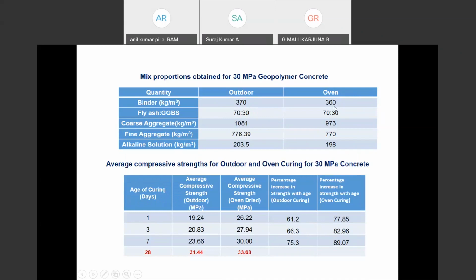If I go for oven curing with the same mixes, means 70-30, here also you can get the 70-30 there. But here if you see, there is only a slight variation of the strength of 2 MPa after 28 days. But if you observe, almost 75% of the strength you are going to get at the age of 7 days due to the polymerization process there.